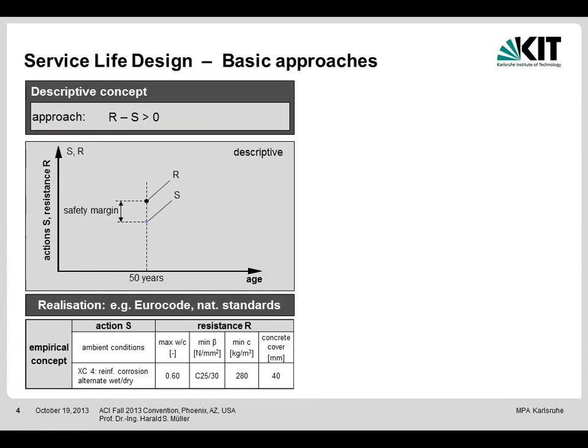Resistance must be higher than actions. And if you plot this in the diagram, you see it's completely different than the one I have shown before. We look to an average age of 50 years. We assume there is a safety margin in between. And the method we apply is that the actions are defined by ambient conditions, and the resistance by some parameters of the concrete: maximum water cement ratio, minimum strength, minimum cement content, and concrete cover.